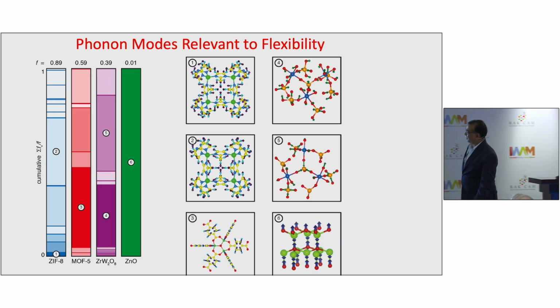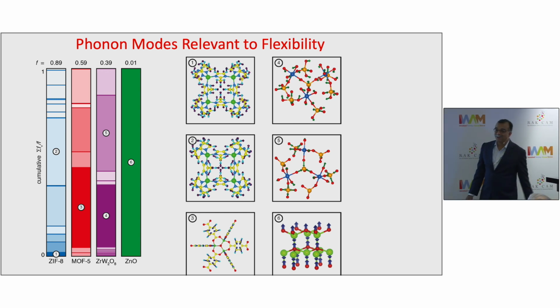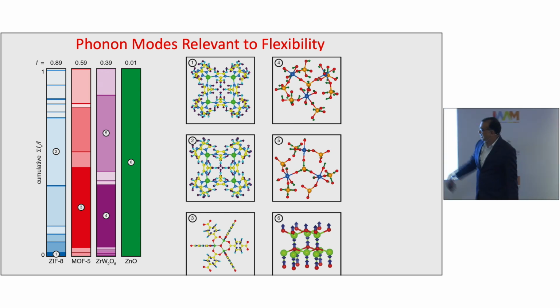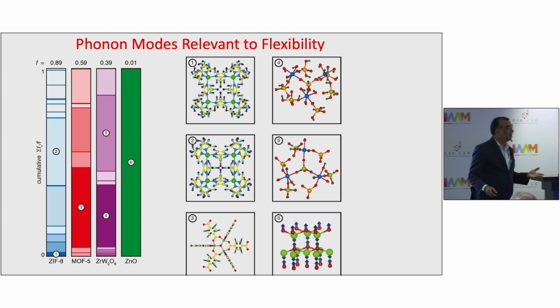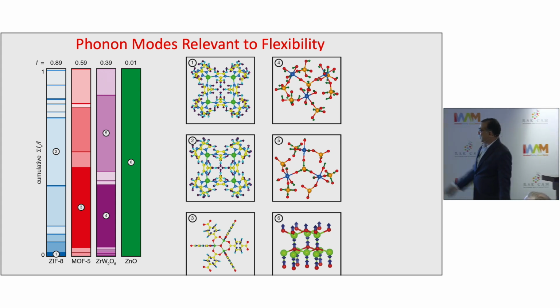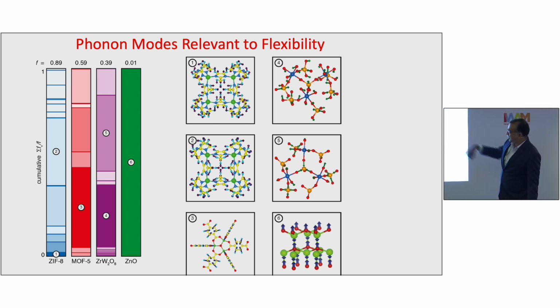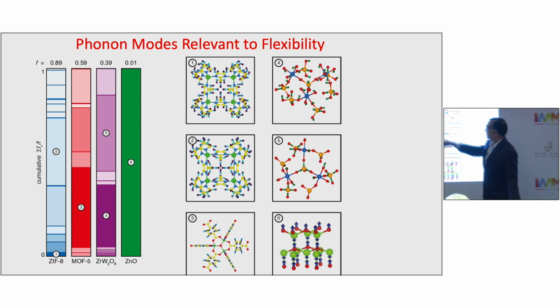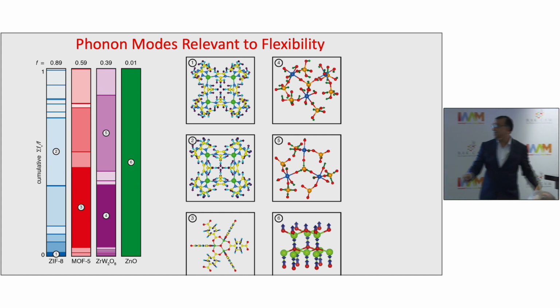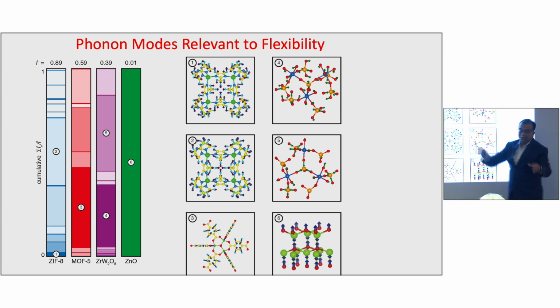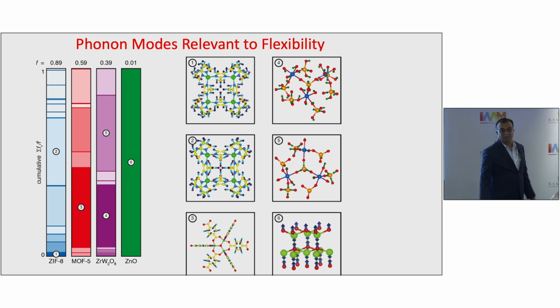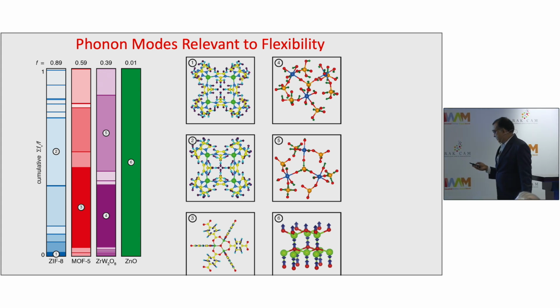And here is a very graphical view of looking at this. On the left side, we are showing a bar chart, whose color intensity says the dominance of phonons. And we have labeled the phonons by 1, 2, which give the most dominant contributions, and their displacements are atomic structural. These arrows basically tell you how the structure changes in response to this deformation and give rise to flexibility.